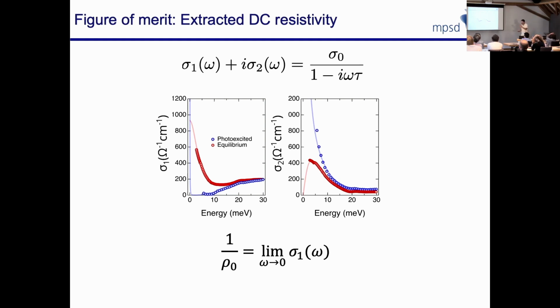The lower in frequency I can measure, the better I can tell you what sigma one is. The sigma one in a superconductor would go to infinity, but even in an equilibrium superconductor, I could only tell you that this is some number 10 to the 14, between 10 to the 14 and infinity. So you determine sigma 1 in a superconductor from sigma 2?